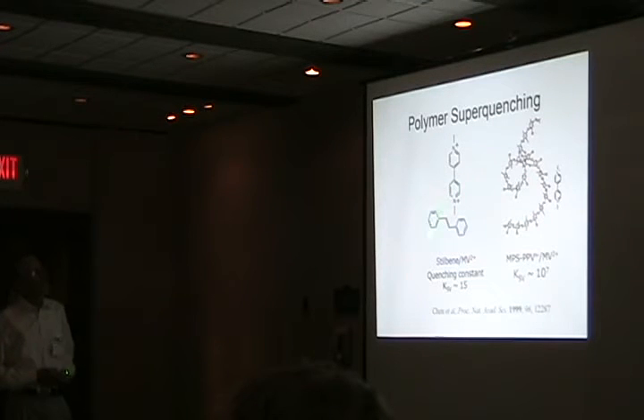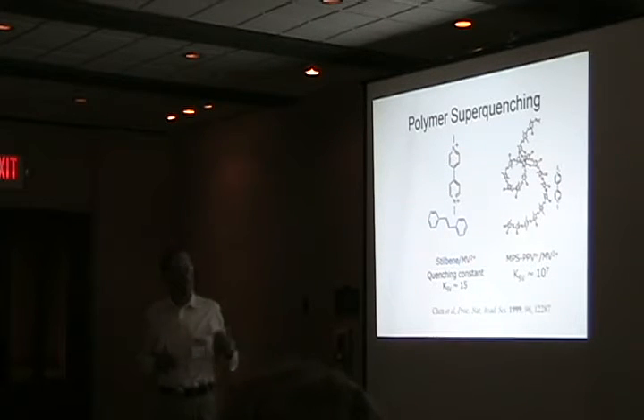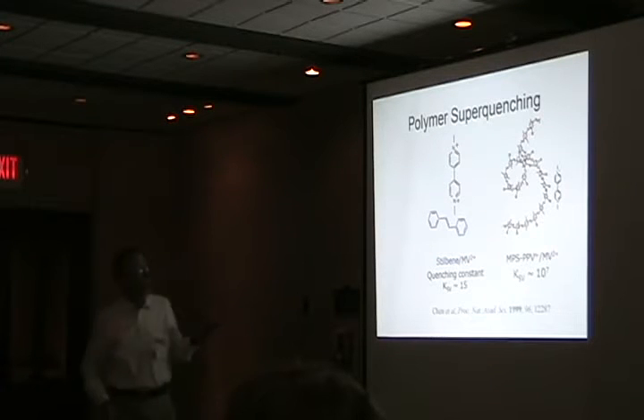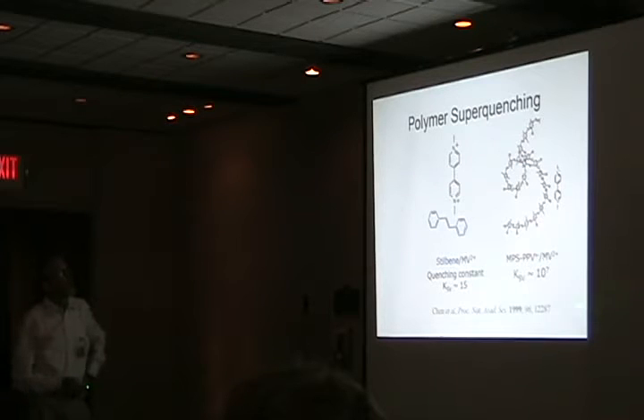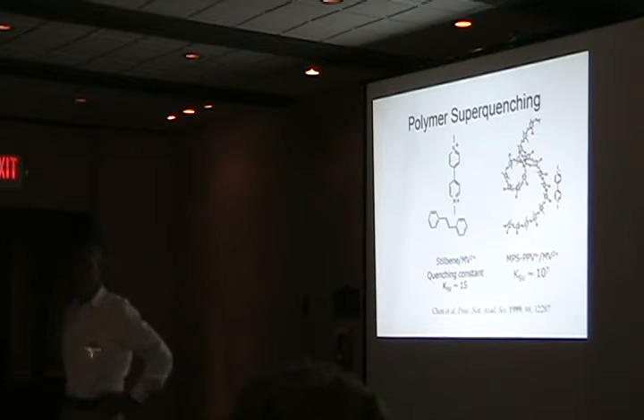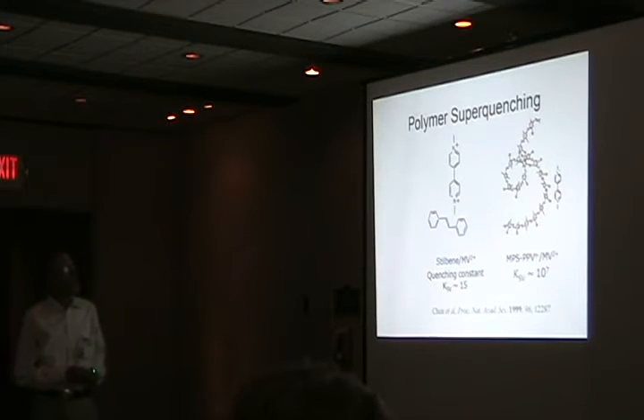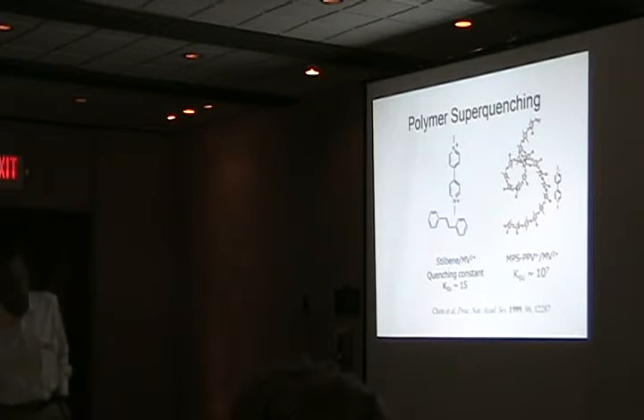Now we found that we could enhance this in a micelle if we add, for example, an anionic detergent. What that does is concentrate the stilbene and the methylviologen on the surface of the micelle, and the quenching constant goes up to about 1,000. So we compared that to the MPS-PPV, and what we found here is that the quenching constant's up to 10 to the 7th. This is, I think, about the highest quenching constant that had been observed when we published this back in 1999. So we had really dramatic quenching enhancement with the conjugated polymer and this electron transfer quencher. And we decided to see if we could couple this to biosensing opportunity, and we found that we could do that.